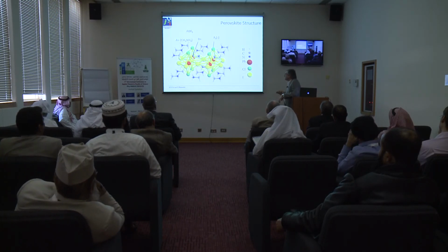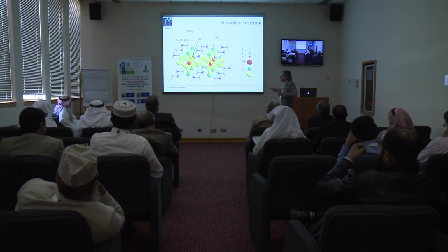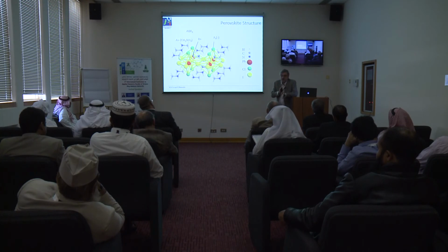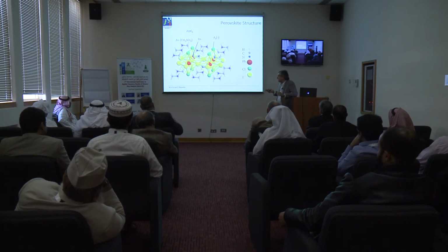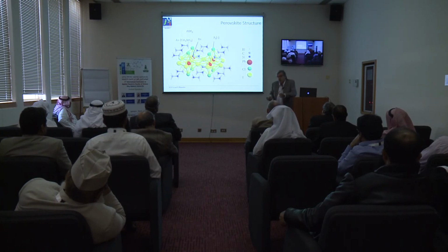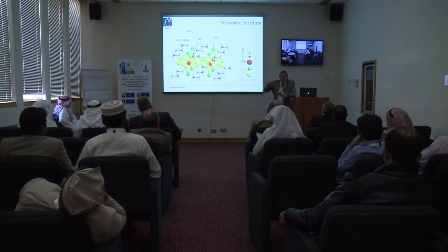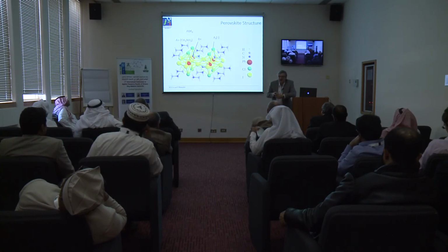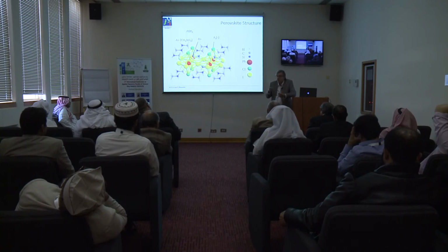So here, what I'm going to tell today is that this is not an electrolyte, of course, but somehow it is, because some of these ions, especially methylammonium, and some interstitial iodides, are mobile. By definition, an electrolyte is something that can move ions, okay? But this will not be really an electrolyte, because in an electrolyte, you don't want to carry electrons. If you want to make a battery, you want to transfer ions, but you don't want the electrons to go through, because this will short, okay?